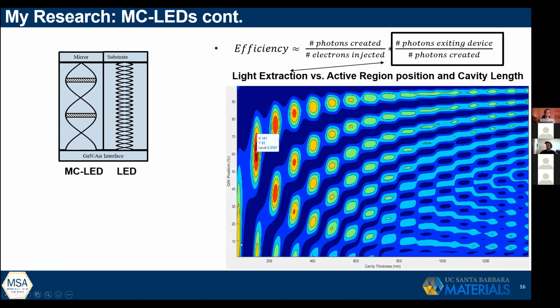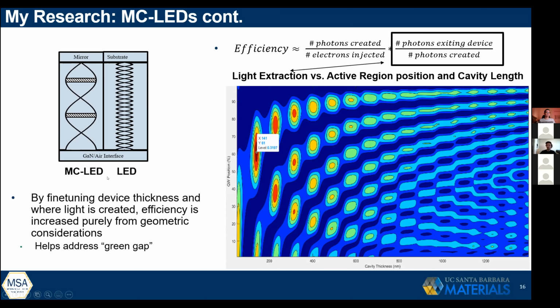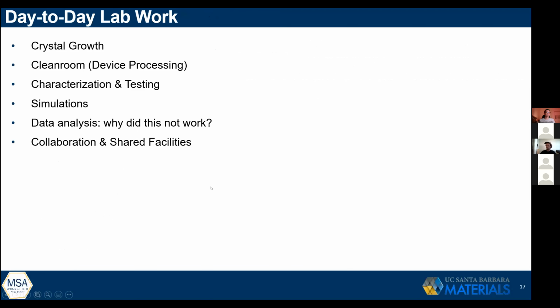You can have only one or two positions where you can place your active region for this to work. And so just by fine-tuning your device thickness and where you're creating your light in your LED, you're able to increase your efficiency purely from geometric considerations based on reflections and things along those lines. And so this helps us address the green gap, which is pretty useful.